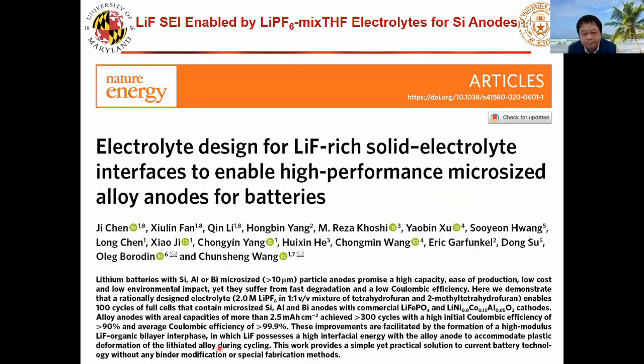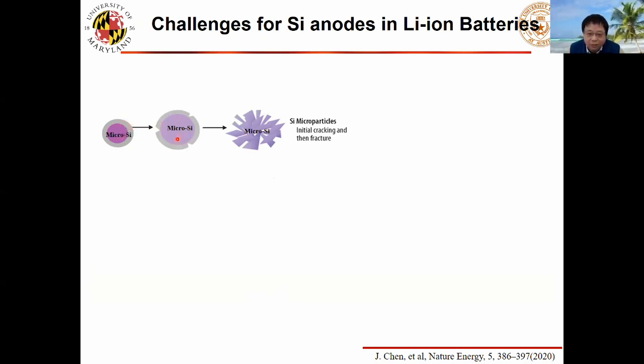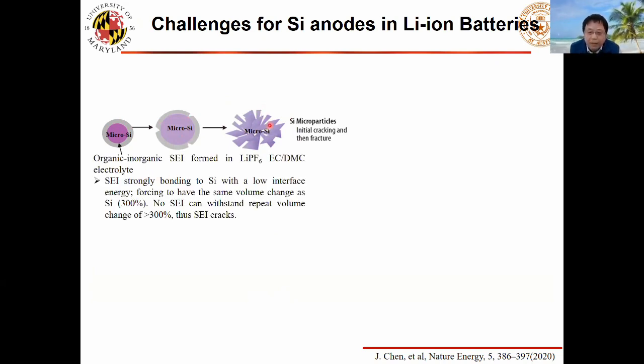This is the silicon work. We use THF to demonstrate the concept. This is a collaboration with Argonne National Lab. Let me talk about the silicon challenge. Traditionally, we have organic SEI on silicon. During lithiation, volume change causes cracking. When the SEI is strongly bonded with silicon, no SEI material can withstand 300% volume change, so they crack. When silicon itself cracks, a lot of electrolyte comes in and forms more SEI inside, creating a composite. That's why the SEI cracks — because it's so strongly bound with silicon.